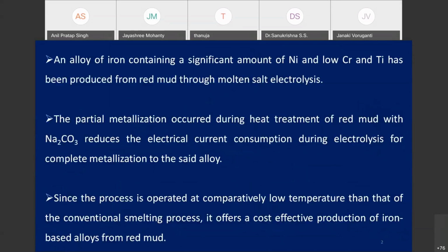So in this topic, we have discussed two types of alloy preparation from two different starting materials. One is titanium slag, another one is red mud. Particularly in the red mud, an alloy containing iron in significant amount with some amount of nickel and low chromium and titanium has been produced. And as you know, iron is a very good structural material.